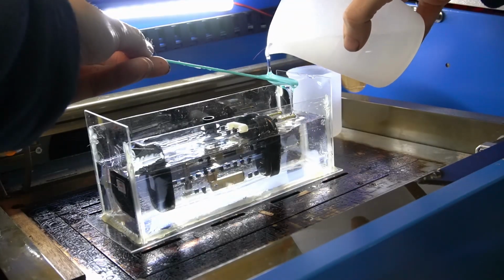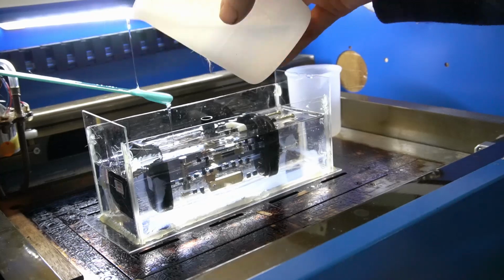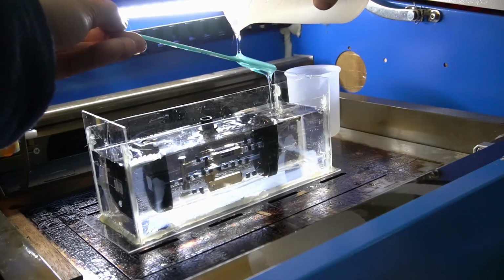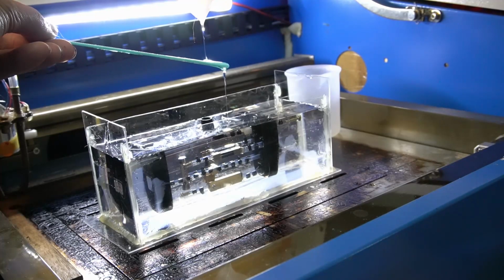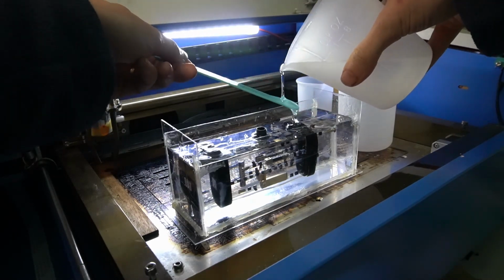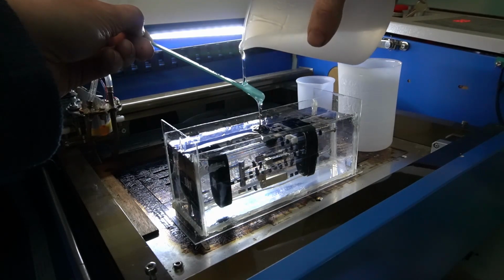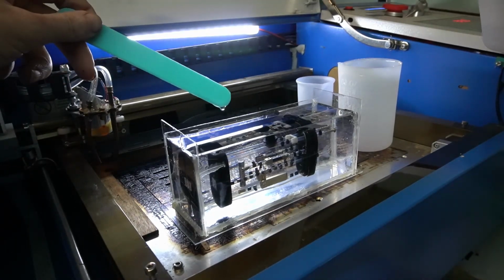So I'm going to complete the layers now, and we are going to pour with bigger gaps in between each layer. Before I was doing it after 20-25 minutes ish, and then ended up really thick really quite quickly, and that didn't give enough time for the exothermic reaction to happen in the green stage. And so the more resin I added, it just got hotter and hotter and hotter, and ended up with a runaway exothermic reaction. But this time I'm leaving an hour and a half plus between each layer, and it's hitting the very end of the green cycle, so it was only just still kind of sticky on top, which might be a little late, but it seems to have worked okay.